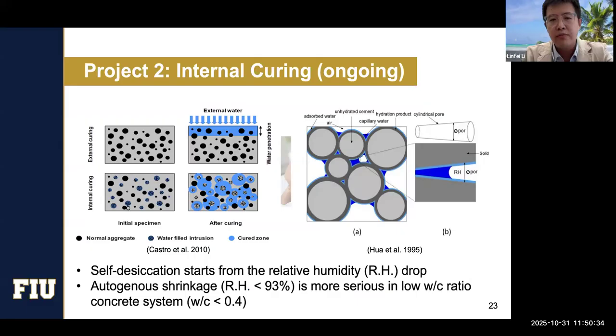A little bit more information. The self-desiccation will start immediately from the relative humidity drop. But consider your cement is hydrating, so the cement is gaining strength over and over, so people did not think at the beginning that would be a problem. But for autogenous shrinkage, people define it as: if you have a relative humidity below 93%, you definitely need to consider the risk of autogenous shrinkage, which will happen to your concrete and generate cracks on it. And as I mentioned, it is specific to low water cement ratio. If the water cement ratio of your system is below 0.4, you have a more serious problem because you don't have enough water in your system.